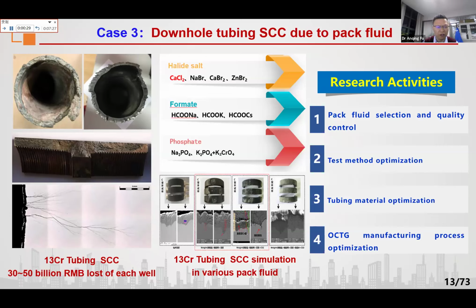We already found a lot of super chromium martensitic stainless steel tubing has experienced severe SCC in the phosphate packer fluid. Here we have found many cases in the field. Also, we have done a lot of tests in our lab. We indeed found the SCC occurred for the chromium stainless steel.